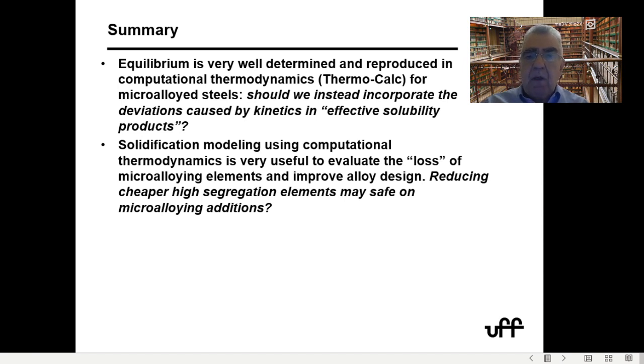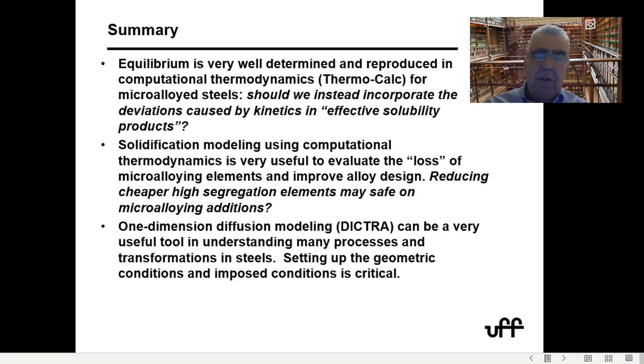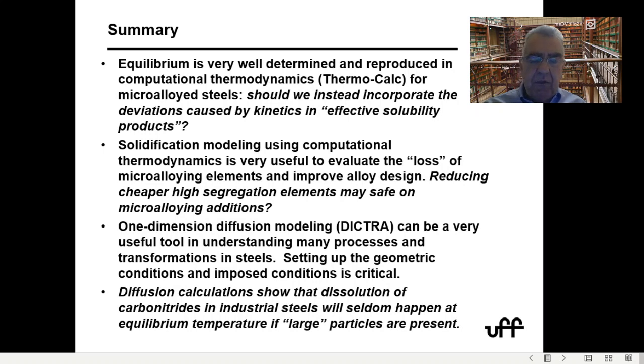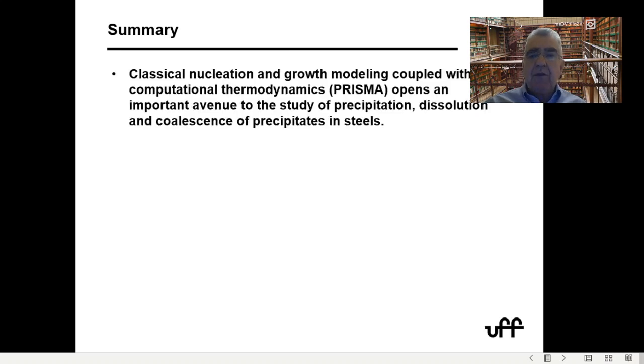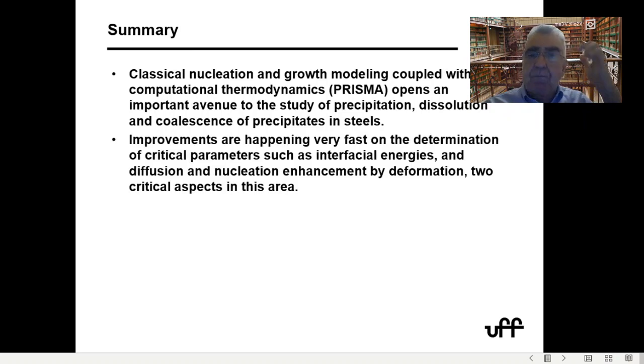Now, solidification model is very useful, and it's helping us a lot to evaluate what we're losing in microalloying elements, because they are not cheap. So we can probably improve alloy design, reduce additions of higher segregation elements, so that we can save on the microalloying elements. The diffusion modeling we use in DICTRA can be very useful to understand, especially the dissolution processes. This is what we've been doing, and it helped a lot to use as much as possible the niobium that we have in the steel. And then the classical nucleation and growth theory is now used coupled with computational thermodynamics. And this is a fantastic avenue to study precipitation dissolution, and I hope that in the next years we'll be able to really do some forecasting, or maybe some careful adjustment, and then developing new steels based on these models.